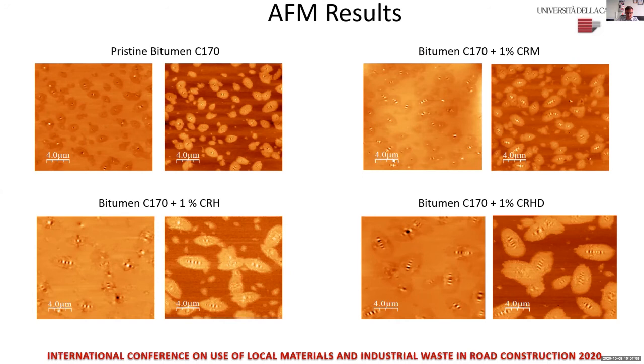You can see here with the magnification that we used that these domain sizes are similar but a little bit bigger with this CRM. With the CRH, we even obtained bigger domains. You can see here, the domains were bigger than 4 micrometers. We have domains of about 5 micrometers in size, which means that this bioadditive increased the rheological properties of